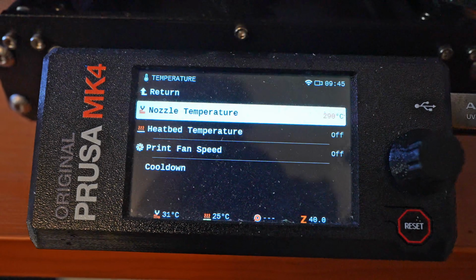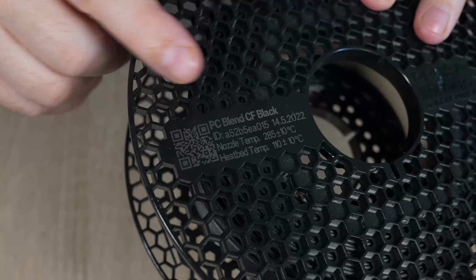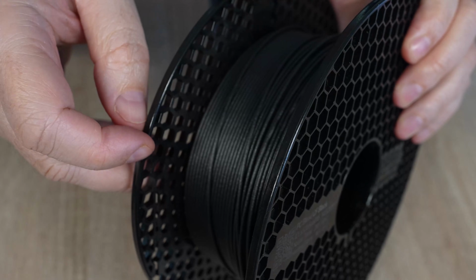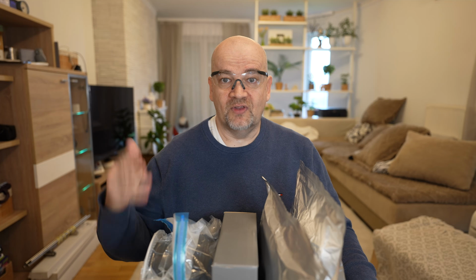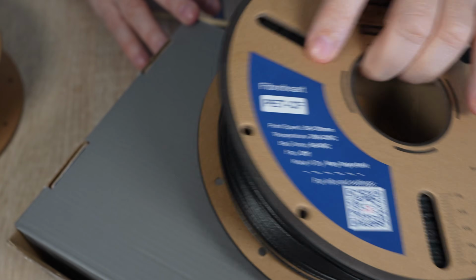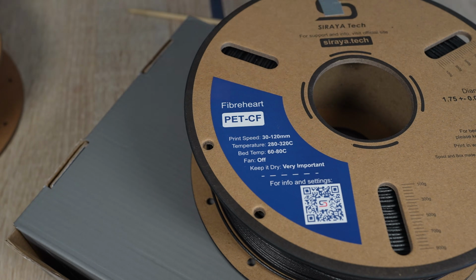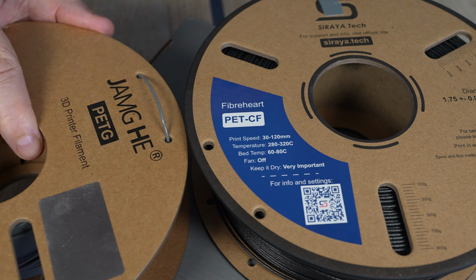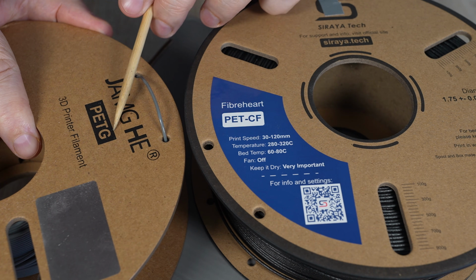And even, for example, the filament PC CF blend can benefit from this extra 10 degrees Celsius. I already tested it. We have much better layer adhesion if we print it at 300 degrees Celsius. Just in case you're not familiar, don't mix these materials with PETG, that's glycol-modified PET. With these, the print temperatures are lower, but also some mechanical properties and temperature resistance are lower too.